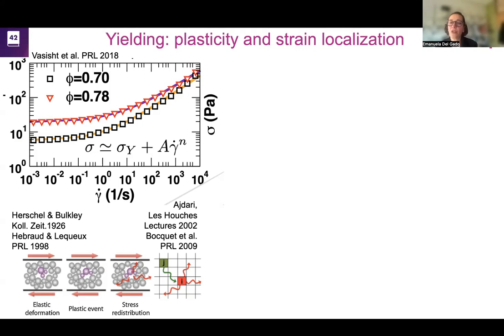it's been understood that in order to get this type of dependence of the stress on the rate at which I'm forcing the material to flow, for example, if I'm applying a rate, is by yielding locally, through a localized plastic process, which then, thanks to the partial stress relaxation that it produces, triggers another plastic process farther away, which then triggers another plastic process farther away. And it's this avalanche, this sequence of plastic rearrangements which depend on each other, that produces an overall very cooperative and collective phenomenon, strongly spatially correlated, which is underpinning this type of rheological flow curve.